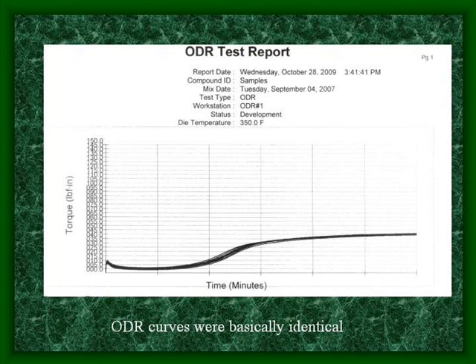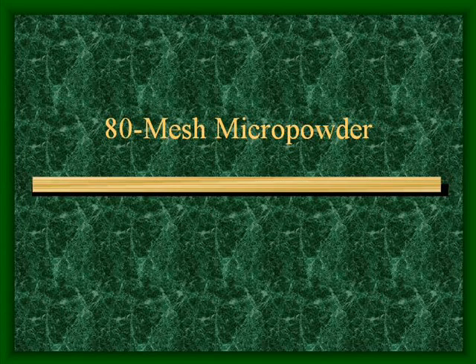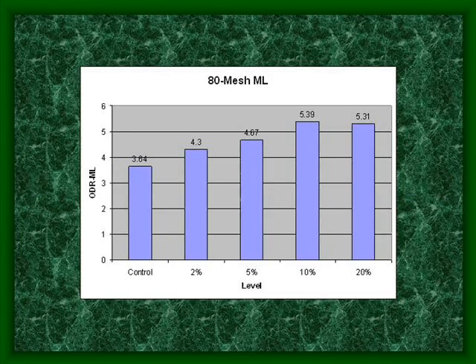Here are the rheometer curves from this experiment. All of the specimens fit within quite a narrow range. The first set of test results were from the 80 mesh samples. In the rheometer data, there was a small difference in ML. ML increased with increasing powder level. This is pretty common when working with micropowders.